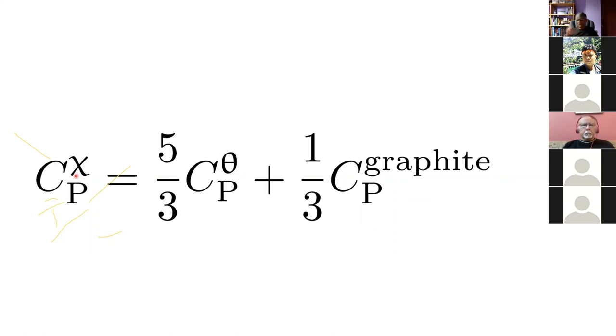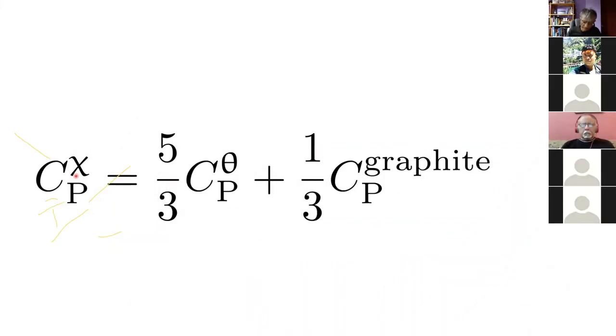The reason those data may be wrong is that there are no good experimental thermodynamic data for these transition carbides. What the authors did was approximate the heat capacity of chi carbide as that of cementite plus the graphite required to change the composition from cementite to chi. That's a reasonable approximation, but the experiments indicate it is not actually possible to get a stable phase field of alpha plus chi in the phase diagram.